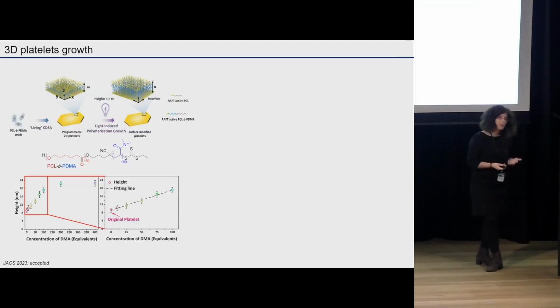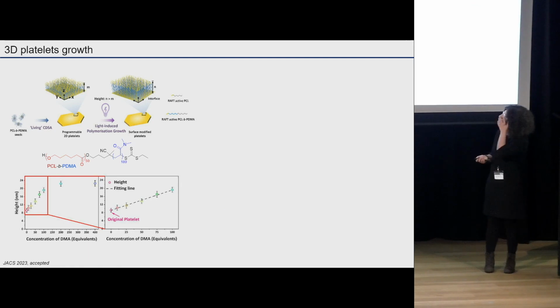And finally, we can also control the nanoparticle in 3 dimensions. So in this case, what I'm showing is the ability to grow the nanoparticle hydrophilic corona in 3 dimensions. So once the nanoparticle is made, you can just add more polymer, and that will grow in 3D. And that is because basically there is this group still present on the nanoparticle surface, and that's the group that will allow you to introduce more monomer and keep growing and keep polymerizing.